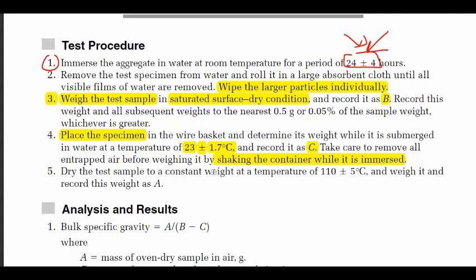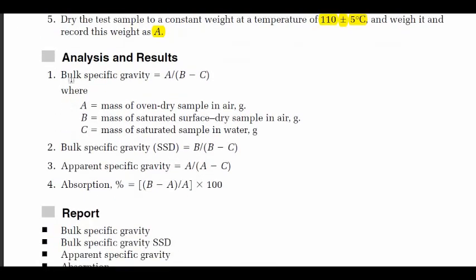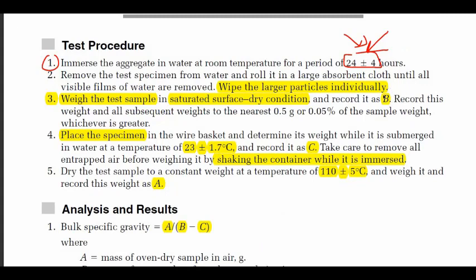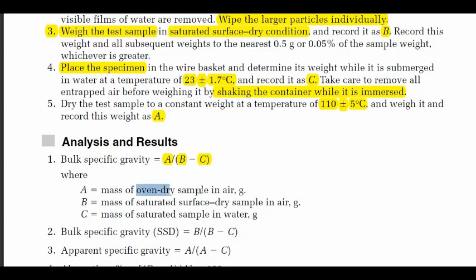And number 5, dry the test sample to a constant weight at a temperature of 110 plus or minus 5 Celsius and weigh it, and record this weight as A. So we have A, C, and B. Then the analysis results are going to be seen like this. The bulk specific gravity is going to be A over B minus C. B is the saturated surface dry, minus C, which is, as we recorded it, the specimen after being submerged in the basket, and then A after drying. Where A is the oven dry sample in air in grams, B is the mass of the saturated surface dry sample in air, and C is the mass of the saturated sample in water.